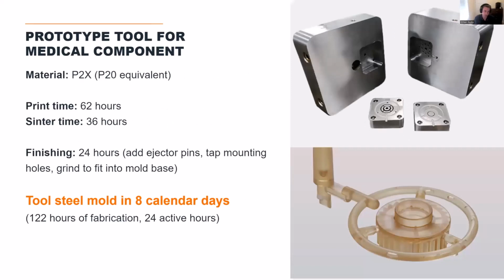What they did is they used their Mantle system, printed these tools in actually our P2X material, which is our P20 equivalent material, 62 hours of printing, 36 hours of sintering here. There was 24 hours of finishing time required. They had to add the ejector pins, which they did via wire EDM. They tapped the mounting holes to mount this thing actually into the mold base, and then they ground it a little bit as well to fit it into the mold base.